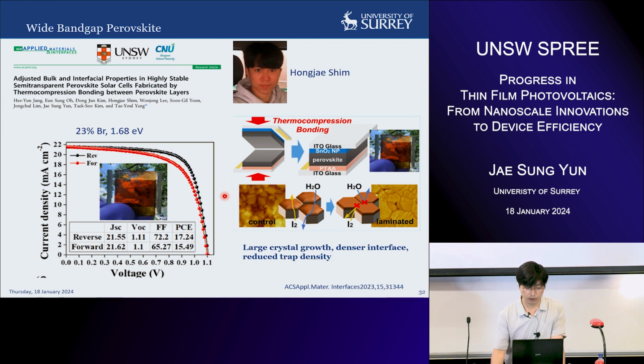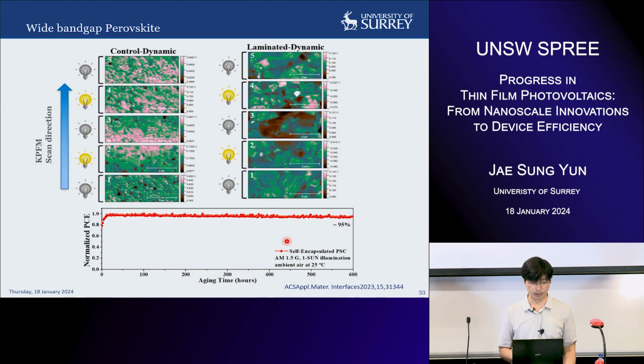And they were able to grow the crystal, sort of recrystallize the perovskites when they bond and press and make a denser interface. We performed the KPFM under the dark and under the light in order to see if there's any phase segregation effect. And we scanned the KPFM with the light on and off. So that's the control sample.